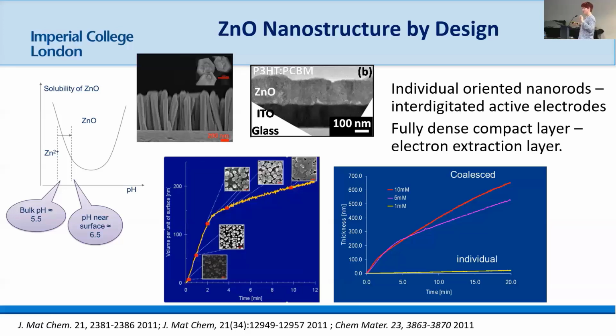So I've created a way that I can absolutely control what I get in my deposit, or I want a really dense film, and this is about 100 nanometers thick. This is an electrode. This is actually a device here, so glass ITO, zinc oxide, and then P3HT, organic solar cell. And this is an electron extracting device. And basically, you go from these quite dramatically different conditions, from having a coalesced system to having an individual system. And we're able to use that dramatically.